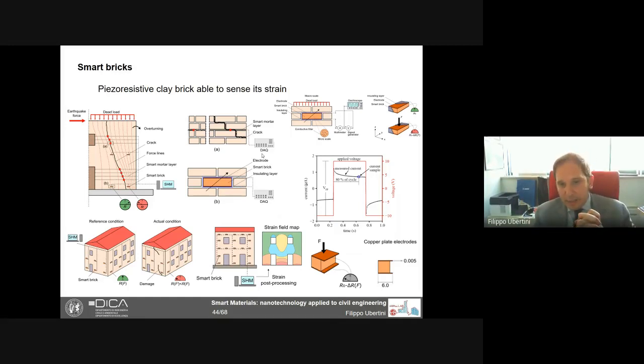And we can construct a map of the strain field, construct a map of the change in the strain field, and see where most changes are located, and that could be the location of the damage. And we could use this to extract features to detect, locate, and quantify the damage. This is more or less the idea.